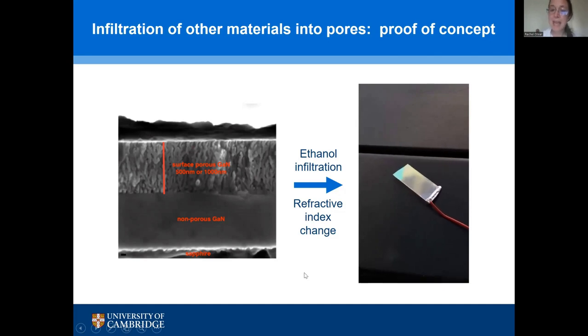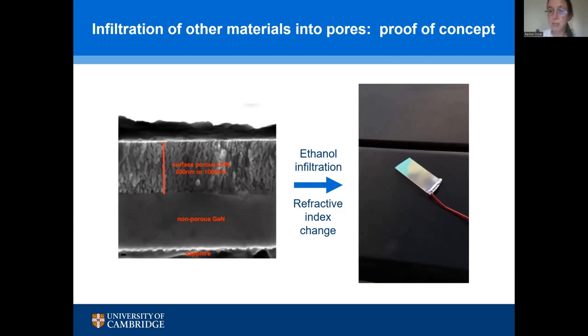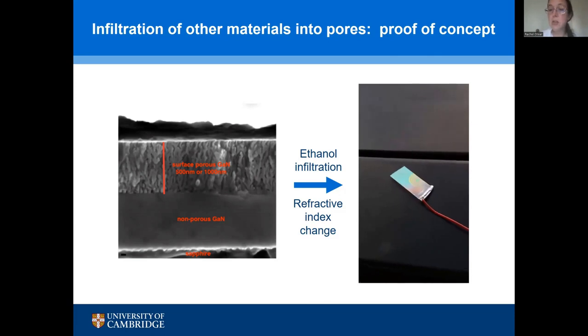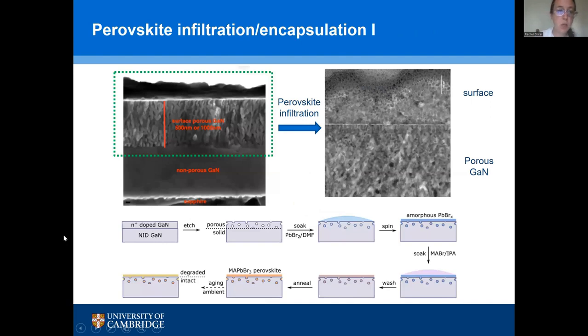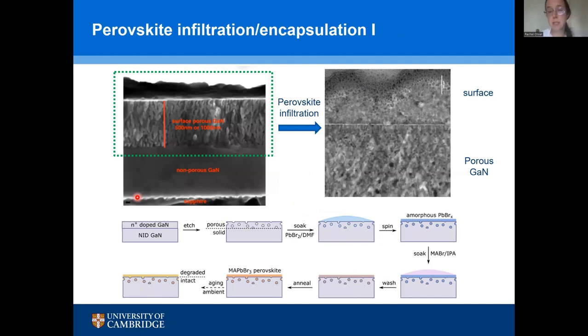So we can definitely get solvents into the pores, but they then just evaporate, and that maybe isn't very interesting. So the next thing we wanted to develop was the ability to get another interesting optoelectronic material into the pores. The material we chose was a perovskite material, one of these lead halide perovskites that's really exciting for new solar cell architectures. Now, the problem with these lead halide perovskites is they're really unstable to air. And we wondered what would happen if we infiltrated them into an optically active porous matrix.